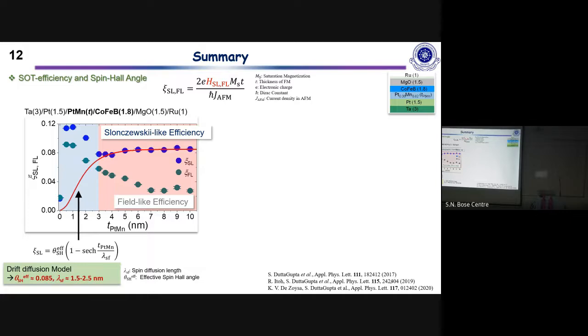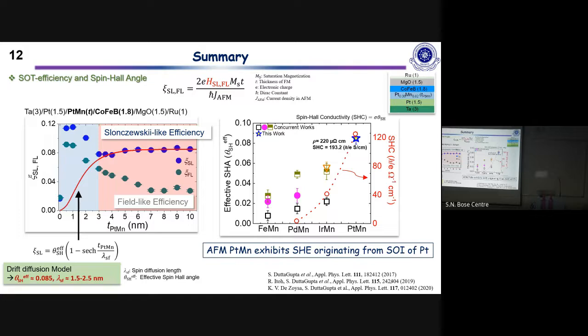And then what we did was, this indicates that the antiferromagnet could be a source of spin Hall effect, which is an important piece of information to have. And then what we can do is plot this spin Hall angle for the various different components of this manganese-based antiferromagnet family.